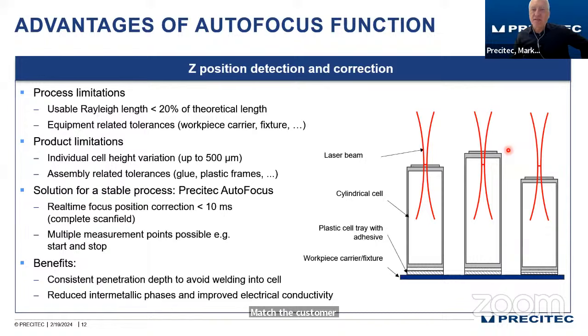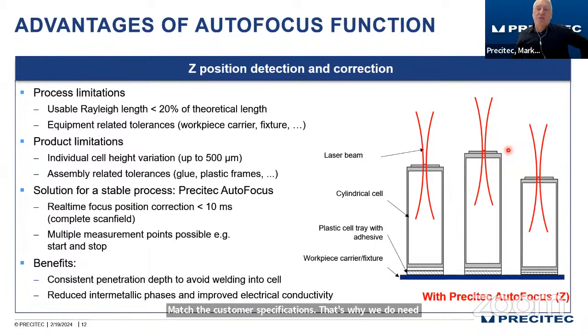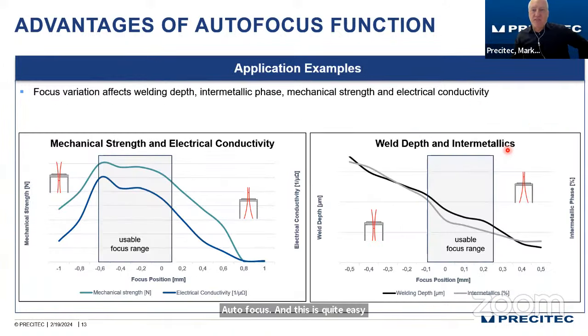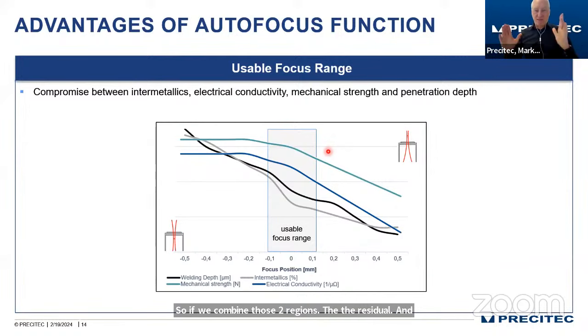That's why we do need to do some measurements, and we do need to apply that autofocus. And this is quite easy with the OCT in the Scan Master. You see that, for example, for the mechanical strength and the electrical conductivity, the usable focus range is different than for the weld depth and the intermetallics. So if we combine those two regions, the residual usable focal range is shrinking dramatically. So we only have plus minus 1 millimeter of residual focus length.